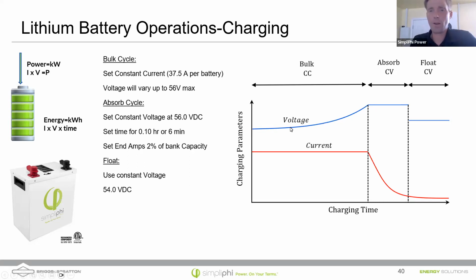So if I'm putting 37.5 amps into a fully discharged battery, I don't have to apply a very high voltage to get that. I might be able to do that at 52 volts. Right? But to apply that same current when that battery gets more and more charged, I have to apply greater and greater voltage on the charging equipment. And you'll see that voltage start to rise as those batteries are charging up. We set the end of the charge cycle at what's known as the bulk voltage, and that's 56 volts max. So once the charging equipment hits 56 volts, we are done with the constant current bulk portion of the charge cycle.